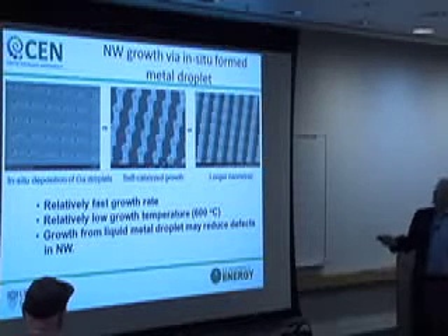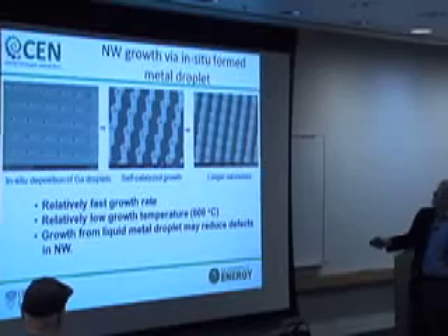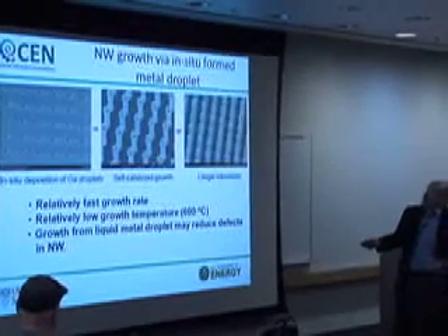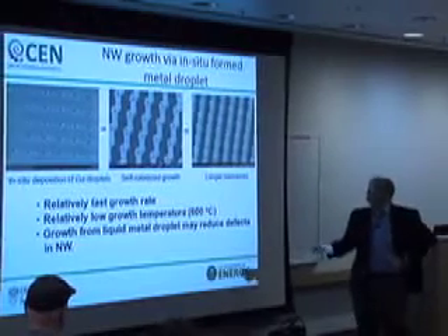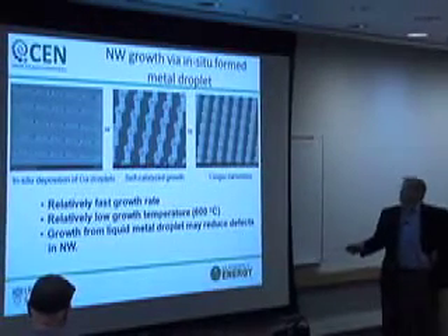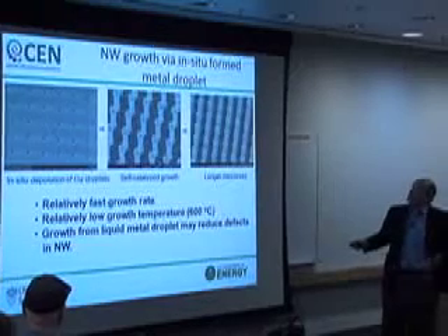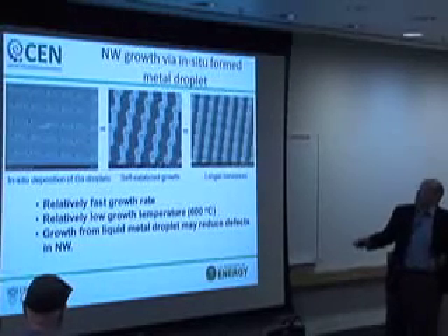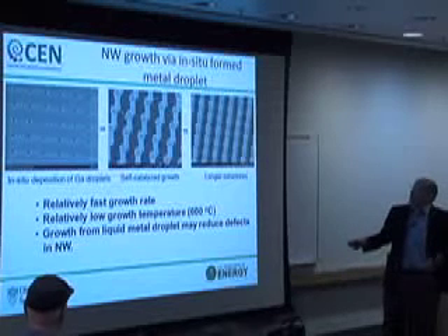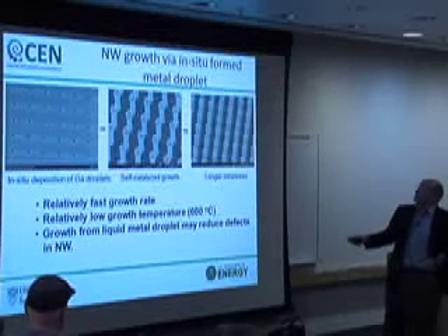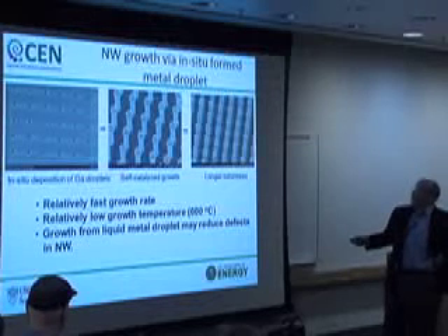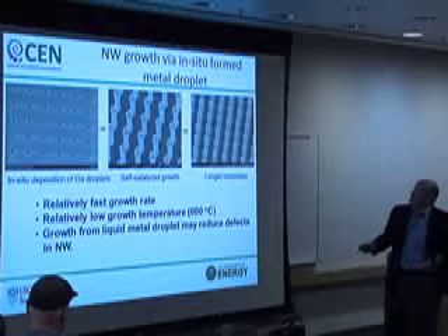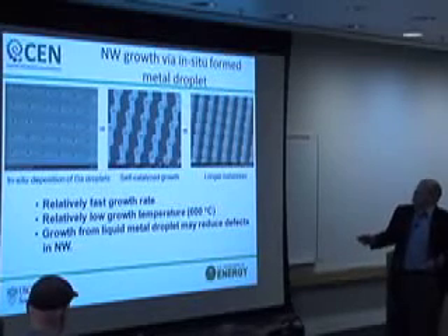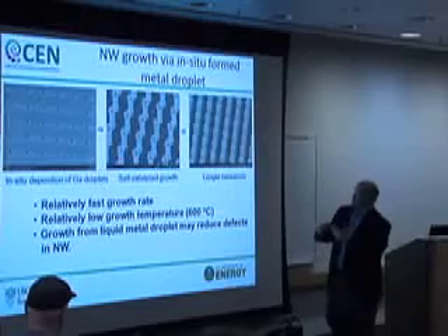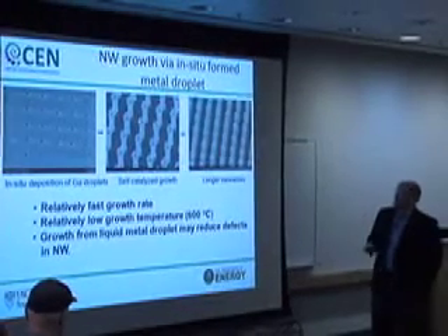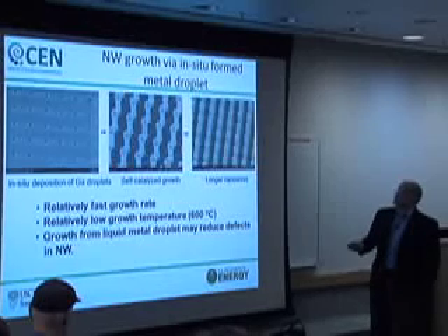We've also grown gallium arsenide nanowires where we use gallium itself as a catalyst, or I call it a solvent, to grow nanowires out of a ball of gallium. So we deposit gallium in the openings on the surface and then grow by MOCVD, and we can form nanorods at actually pretty high growth rates and quite uniformly. There doesn't appear to be a great advantage to this over the direct selective area growth in terms of the properties of the material, so we haven't focused a whole lot on that.